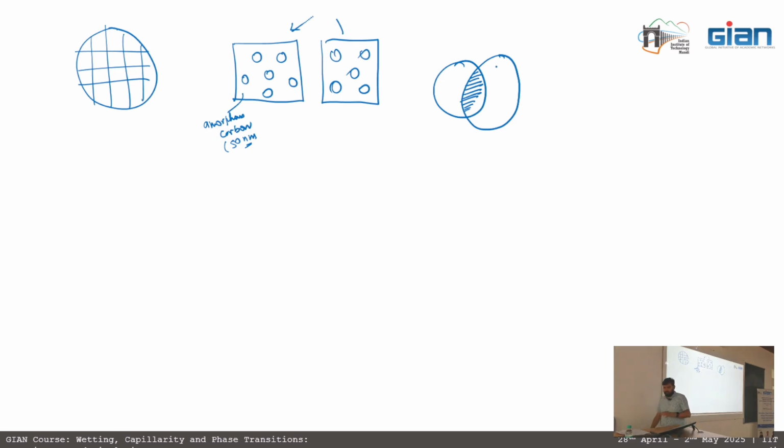So this is a merit, that this can be used multiple times. If you make one good liquid cell, you can expect somewhere around 500 water pockets in that. And it's difficult to observe all the 500 water pockets in one go. So you can maybe irradiate one section of the sample first, observe the bubbles or any of the phenomena which you want to see, and then maybe switch to another in the next experiment. That's how you can do it.